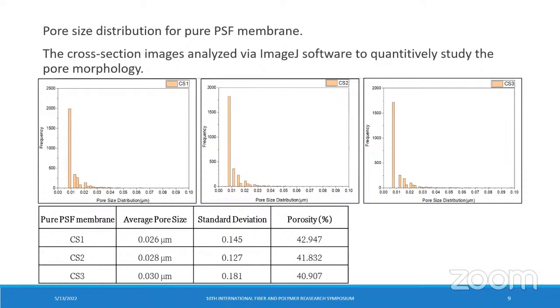The cross-section SEM images are analyzed using the ImageJ software to obtain a quantitative analysis of the pore morphology. We have randomly selected 3 samples of the membrane for the analysis. Here we are showing the results in figures. We are showing the pore size distribution for the 3 cross sections, and we can see that the results are consistent for the 3 samples.